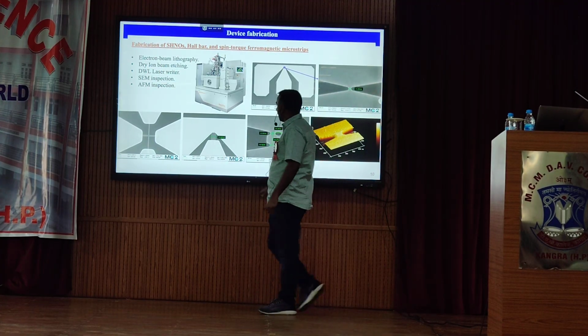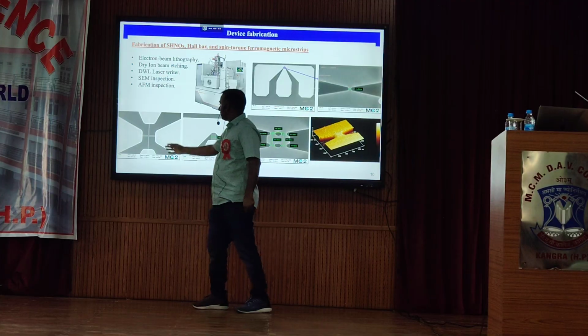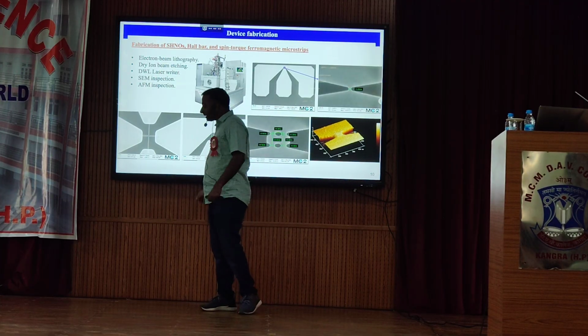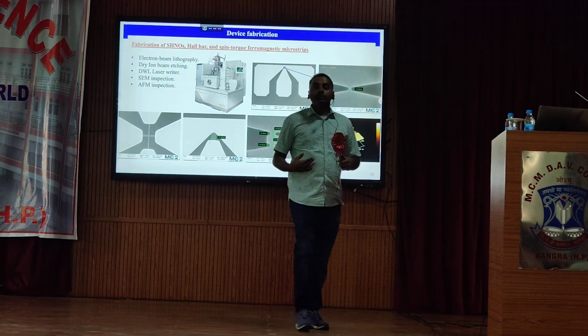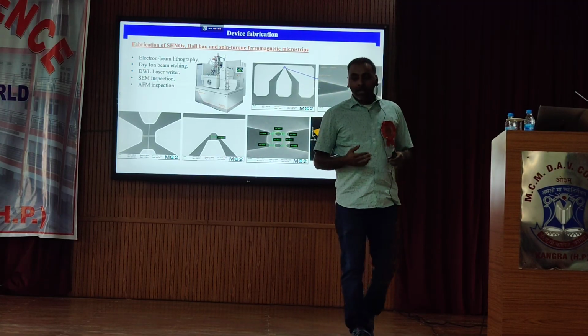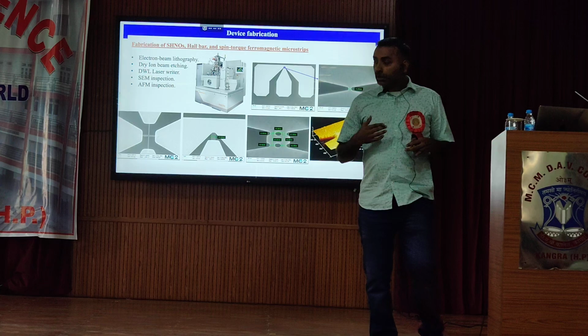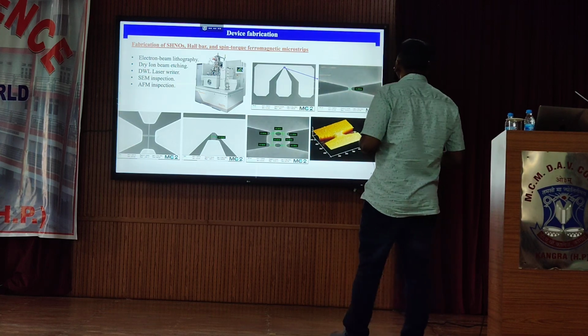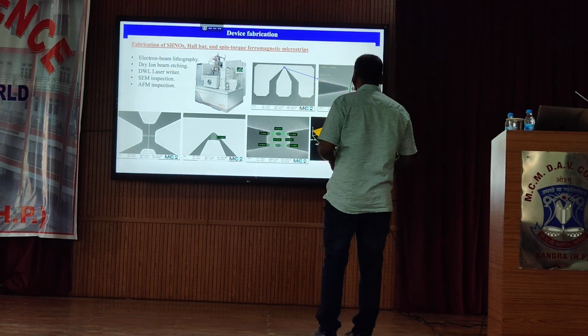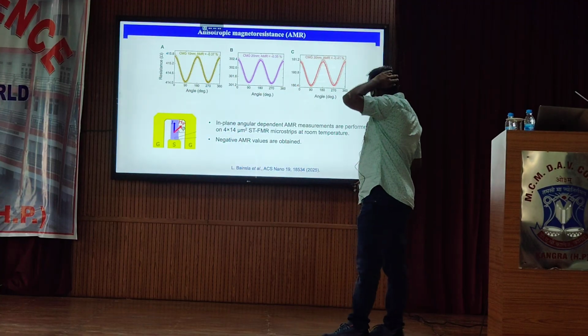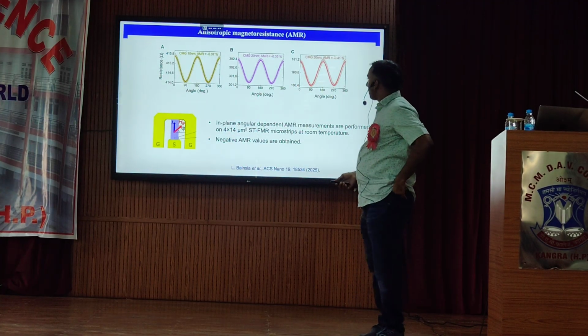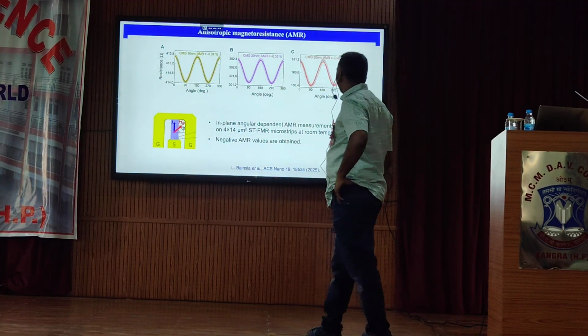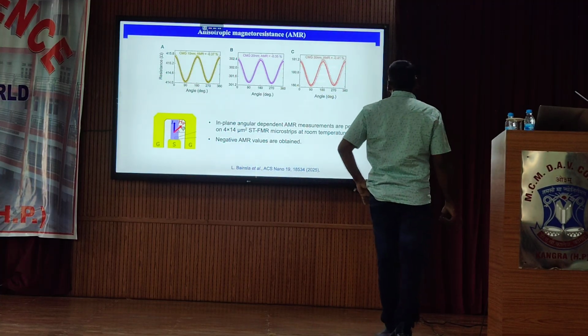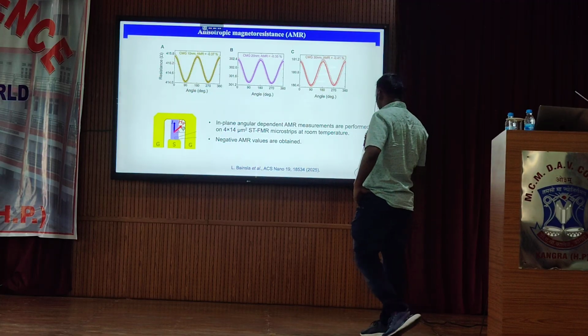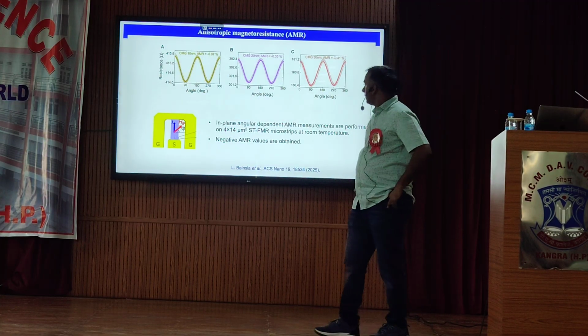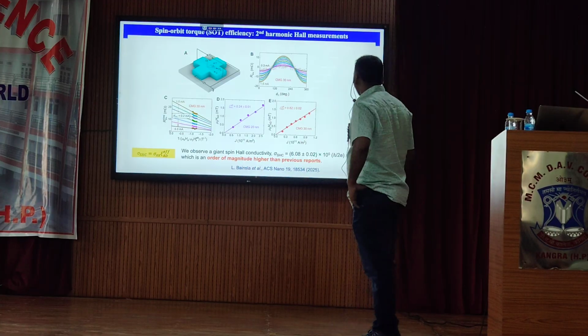We have also devices like this, microstrips and Hall bars. These microstrips and Hall bars we use to estimate the spin orbit torque efficiency. And as I said before, spin orbit torque efficiency of the material is important if we want to reduce the power consumption of the devices. So before measuring the spin orbit torque, we first measure the anisotropic magnetoresistance, because it's an essential property that we require before getting any spin torque ferromagnetic resonance signal. And we can see very nice anisotropic magnetoresistance for our samples.